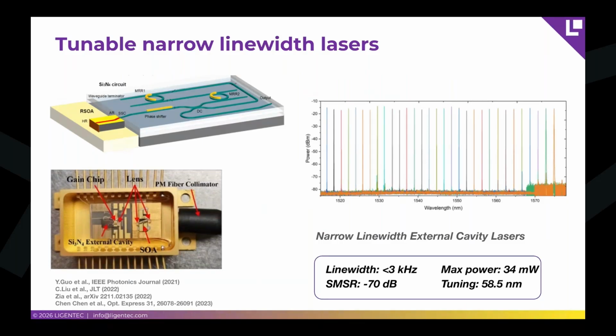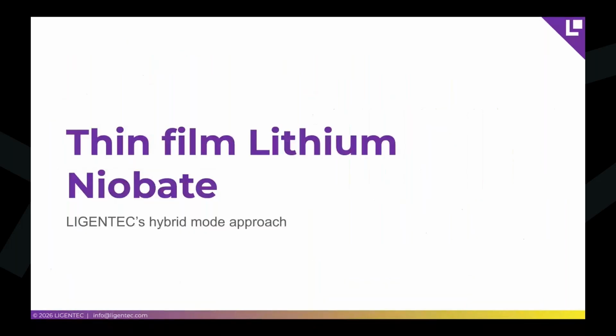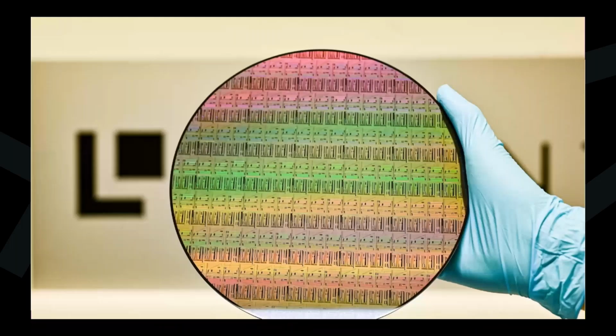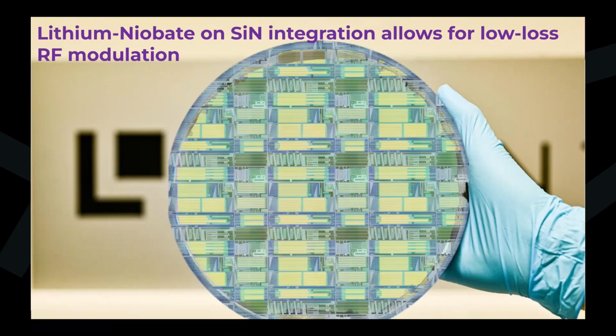But what is missing in a low loss platform is a high speed modulation approach, and here we're looking at thin film lithium niobate. So we're starting from a low loss silicon nitride wafer and integrate thin film lithium niobate on top of the silicon nitride waveguides that allow for low loss RF modulation. And how does that look like?